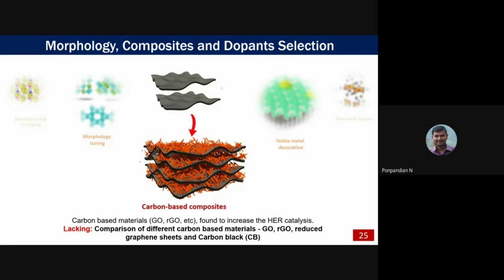You all know that the carbon, based on the allotropes of carbon, you can get 4 different types of nanomaterial. I hope you all know that. The first example for a 3-dimensional carbon is graphite. That is a 3-dimensional structure. From that, if you remove one layer of carbon from the graphite, that will give the graphene. That is a 2-dimensional material. Now, this 2D material, you can fold it in that way, you can get a nanorod or nanotube. In that way, you can get a 1-dimensional carbon nanotube or nanorods. And again, from that graphene sheet, you can make carbon dots. That is a 0-dimensional material or quantum dot. In that way, using carbon, you can make 4 different types of nanomaterial. We are using the 2D material, that's graphene, for our application to make the composite.